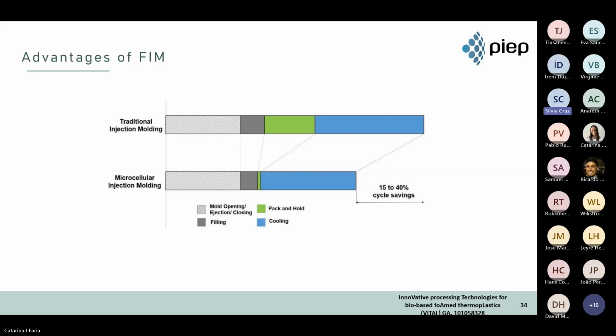Another advantage is the lightweighting, reducing part weight typically between 10 to 30% due to the cellular structure. This will lead, obviously, to lower material use, reduced costs and material saving. Also, this technology allows the reduction of sink marks and warpage due to the gas expansion that compensates for shrinkage and improves dimensional stability.